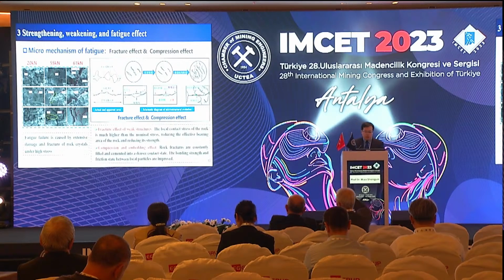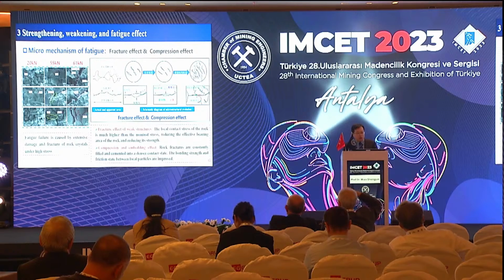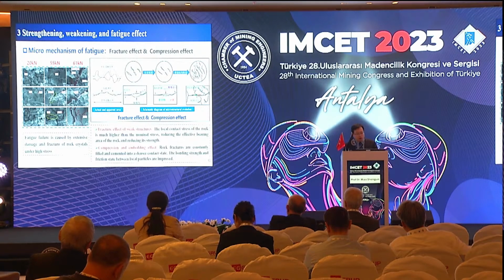And then we use electron microscope scanning techniques to observe the fracture morphologies of siltstone under different test conditions. We found that when the upper limit load is low, the cracks propagate along the weak structures and were compacted obviously during the elastic deformation stage.